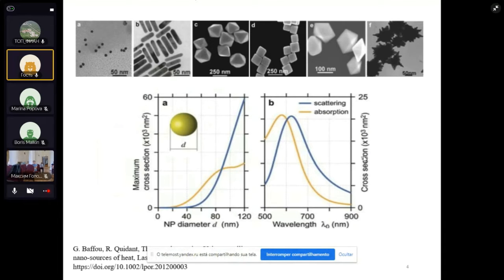One is by a French group, Baffou and Quidant. And of course, the interaction of metallic nanoparticles and an emitting species will depend a lot on the concentration and the shape of the metallic nanoparticles. And one important point that I would like also to call your attention to is that they have shown that depending on the size of the nanoparticle, the extinction coefficient is composed of one part, the absorption coefficient, here in orange, and a scattering part, which is in blue. And you may see that in the range where we usually work concerning the size of the nanoparticles, the absorption component dominates.